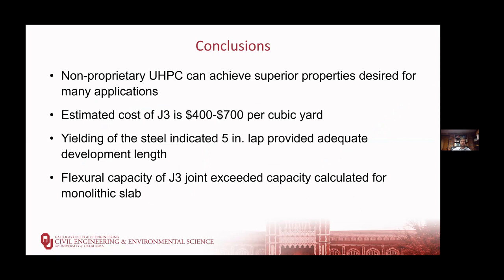So in conclusions, the non-proprietary UHPC can achieve the superior properties desired for many applications. It has an estimated cost between $400 and $700 per cubic yard, depending on the fiber content, compared to several $1,000s for the proprietary materials. And in our structural tests, we found that we yielded our reinforcing steel with just a 5-inch lap splice and got a strength of our joint that exceeded what we calculated for a monolithic slab.